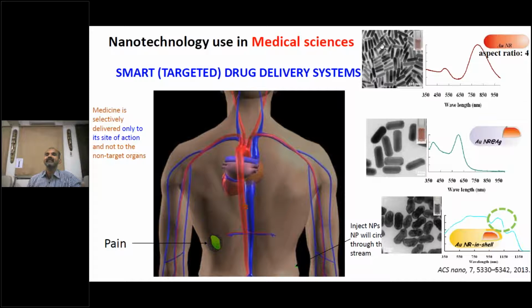One reason is that the aspect ratio cannot be maintained. When you increase the size of the longitudinal growth, the transverse growth also will increase. This is controlled because of CTAB. Certain molecules bind specifically to one of the faces of the particles, so they will not allow one side to grow and it grows on the other side. But when you allow it to grow for a longer time, it will grow longer, and also a little bit it will start expanding. So you will not get the NIR shift that you are expecting at 1100.